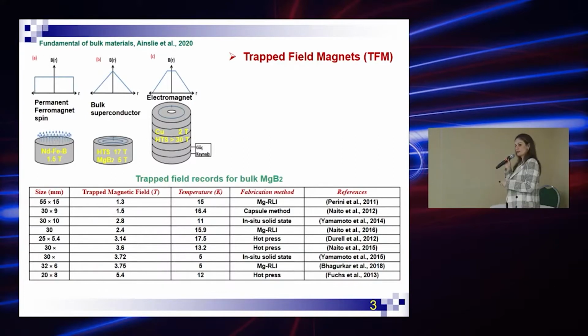But its counterpart MgB2 has a homogeneous JC distribution within the sample, which causes a homogeneous trapped field distribution within the sample. It clearly contrasts with the cuprate materials. This table shows the records for bulk MgB2, and it is clearly seen that the target trapped field value is 3 Tesla at maybe 20 Kelvin, which appears like a modest value compared to cuprates.